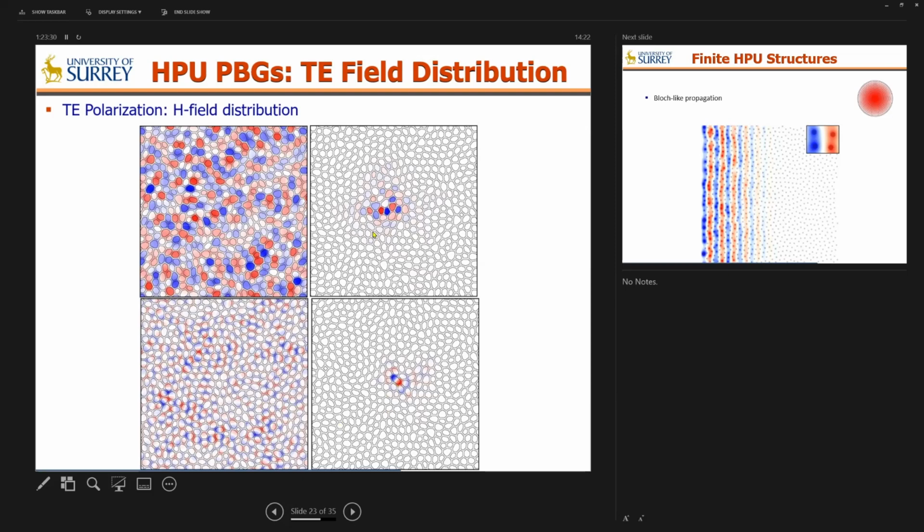So clearly, for modes below the gap, we put together an ensemble of resonances which excite the inside of each of the cells, while modes above are created by putting together an ensemble of resonances with a nodal plane in the middle of each of the cells.